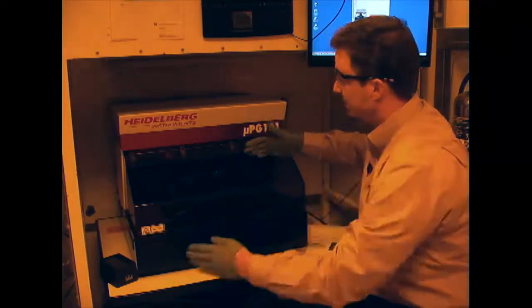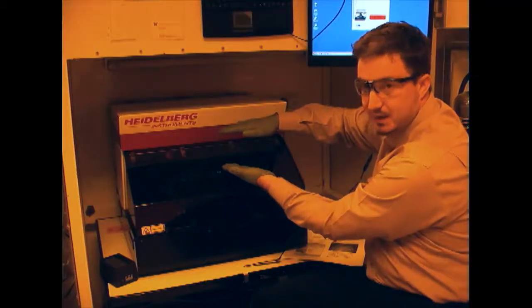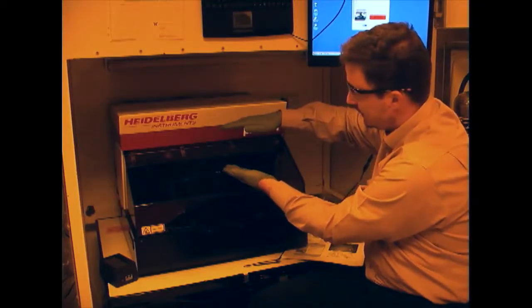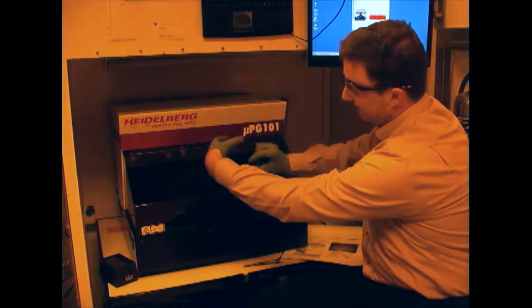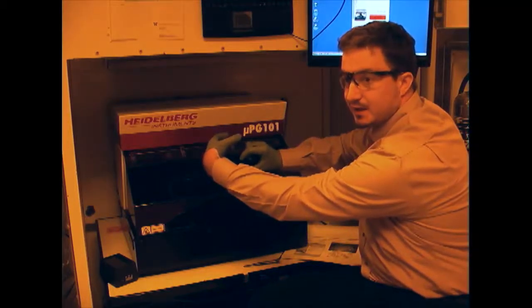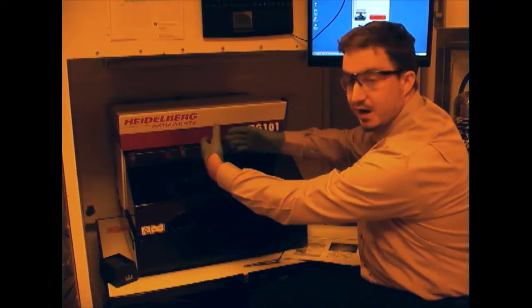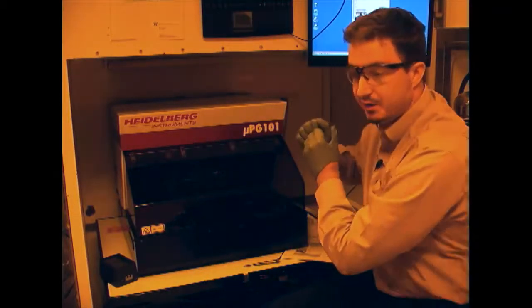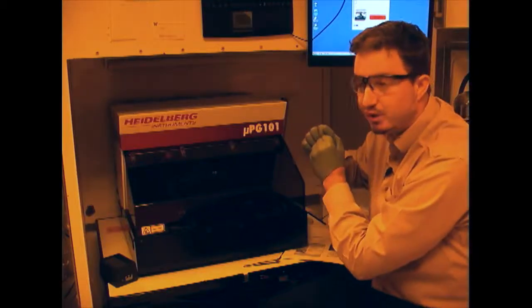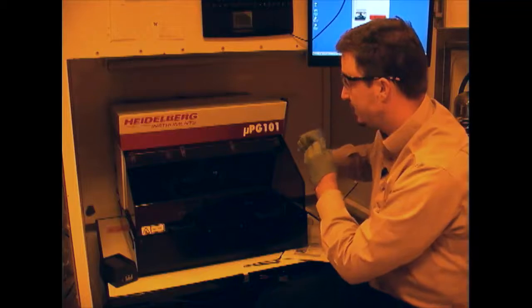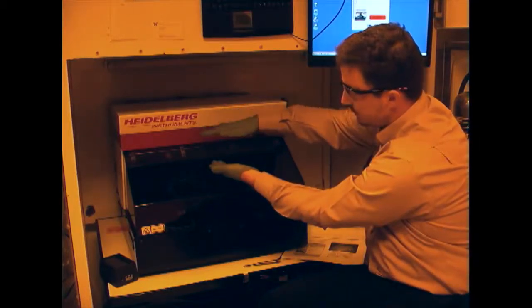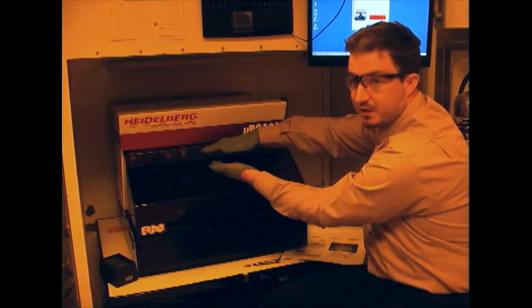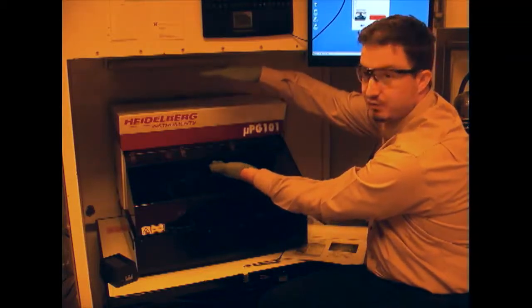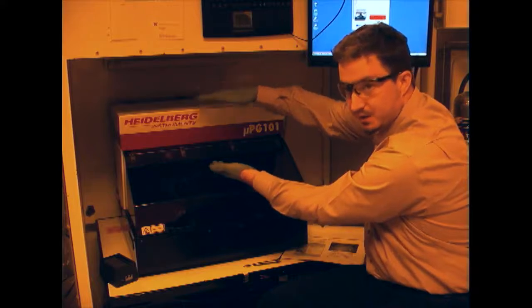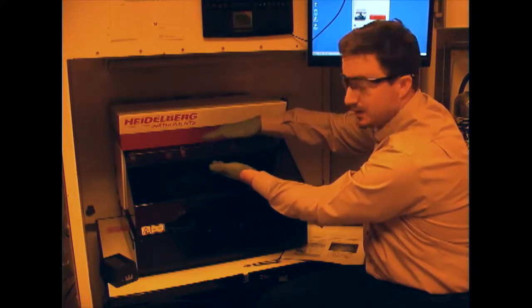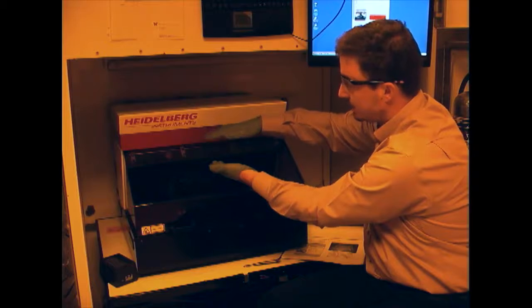In addition, there's a piezo in the Z axis, and the way this is working is the lens has an aperture with a known gap between the lens and the substrate. We're blowing air down this aperture and monitoring the pressure. Because the flow rate is fixed with the air coming by the aperture, if the focus stage moves too close, the pressure rises and the piezo backs off. If the lens moves too far away, the pressure drops and the piezo moves back in. That's how we compensate for irregularities in the surface with the focus routine.